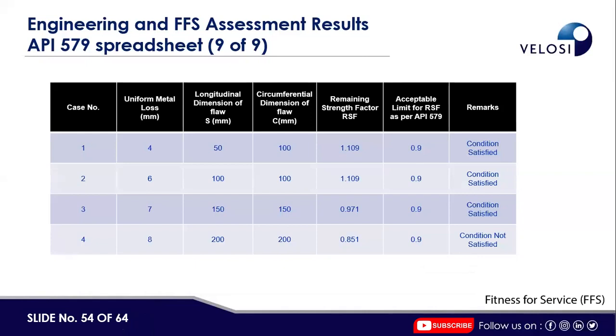So under Case 1, for example, if you see the FFS results, the defect size, uniform metal loss 4 mm, 6 mm, 7 mm or 8 mm, then the longitudinal dimension of the flaw 50 mm, 100 mm, 150 mm, 200 mm, circumferential dimension of the flaw 100, 100, 150, 200. So the RSF or remaining strength factor is 1.1, 1.1, 0.971 or 0.851. So the first three conditions satisfied, condition not satisfied. In this way we can limit or identify the target defect length, which could be acceptable up to what depth level. So in this way future monitoring of the equipment can be done easily.